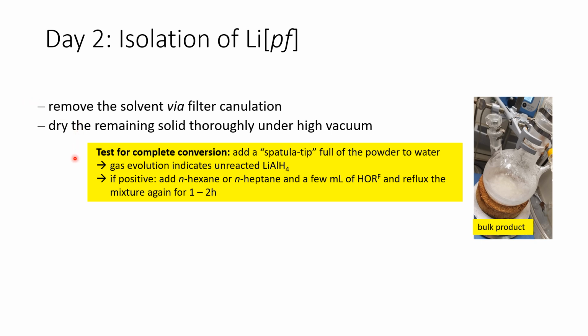To simply test for complete conversion, we can add a small spatula of the colorless powder to water. If we still see some gas evolution, this is a strong indication that we have unreacted lithium aluminium hydride in the mixture. What we can do then is add hexane or heptane as well as a few milliliters of the alcohol and reflux the mixture again for 1 to 2 hours until we don't see any dihydrogen evolution anymore.